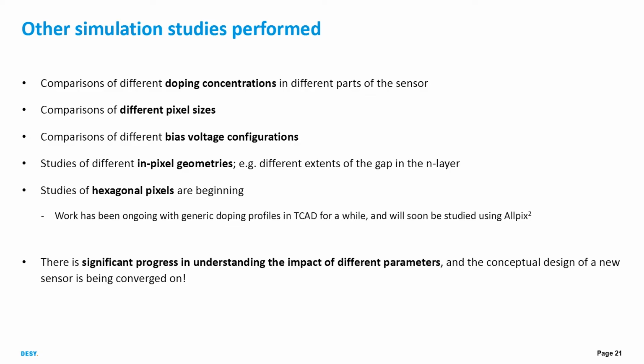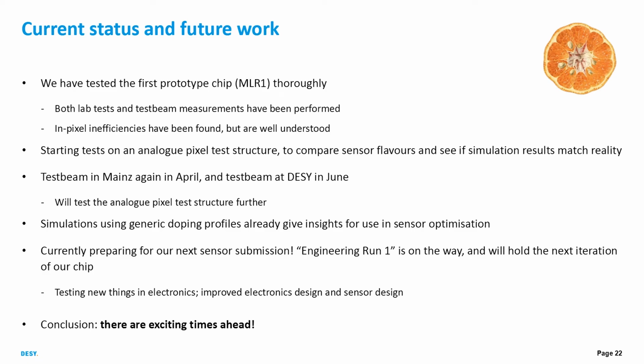And this leads on to the conclusions and future work. So we've tested the first prototype chip thoroughly, both in labs and at test beams. We found some in-pixel inefficiencies, but they're well understood and will be fixed for the next submission. We're starting tests on an analog pixel test structure, which will enable us to compare sensor flavors and also see if simulation results match reality. And we're going back to Mainz in April for another test beam, and then we're doing a test beam in DESY in June, where we will test the analog pixel test structure a bit further.